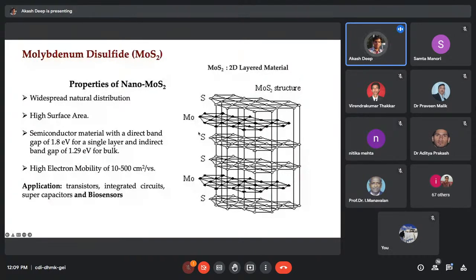It is a semiconductor material with a direct band gap of 1.8 eV for single layer and an indirect band gap of 1.29 eV for bulk. So this property can be used to fabricate sensors, and it has a high electron mobility of around this value.